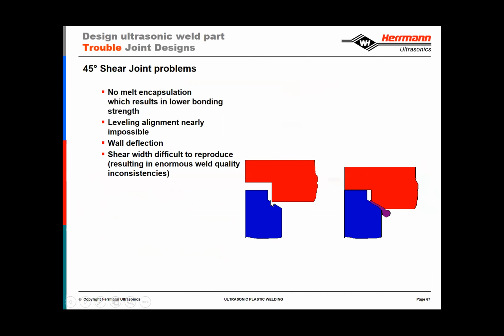The problem becomes in dimensional tolerancing. So imagine if the blue part were a little bit larger, or the red part were a little bit smaller, or in the worst case, both the blue part is larger and the red part is smaller. The interface, instead of being here, will move down to this area. So therefore it reduces the amount of collapse that you can put into the part. So for dimensional issues, we don't recommend this shear joint, but rather our mash joint, where this angle then would be inverted.